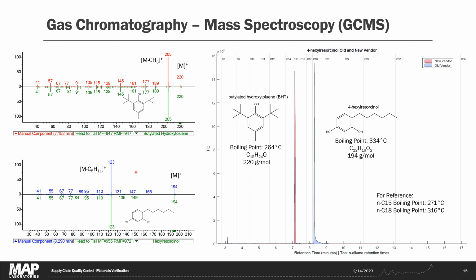The data collected from our samples, here shown in blue, matches the NIST reference spectrum for hexylresorcinol. And for our new vendor, we have this spectrum we collected in red, and it matches this green spectrum from our NIST database. If there had been additional contaminants in here, we would have seen more peaks from the other compounds. And if we zoom in on this butylated hydroxytoluene, we'd be able to see a couple other peaks down in there.